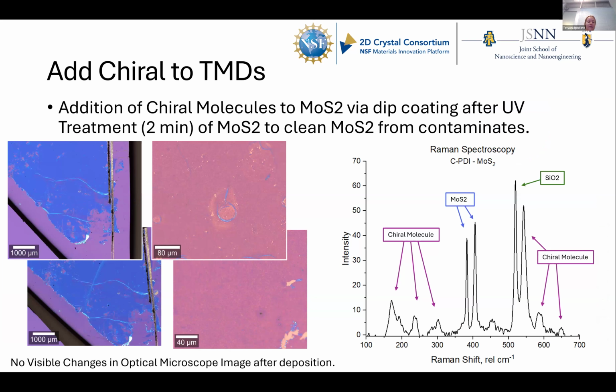Okay, and then when I came back to JSNN, I decided to start adding the chiral molecules. So I have the left and the right. This is the left chiral molecule that I'm showing here. To add the chiral molecules, I took my MoS2 and UV cleaned it for 2 minutes to remove all excess contamination and free the bonding up for the chiral molecules. But that did not change the structure. That's what I'm showing with the left images, before and after deposition.